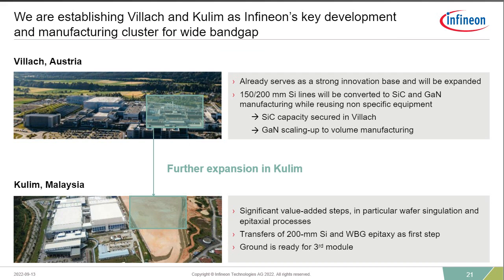And just highlighting the facilities here. We'll have a dedicated 150 and 200 millimeter production line for silicon carbide in Austria, and then the new facility coming online in 2025 in Malaysia, and sharing manufacturing. So this site in Malaysia alone, if it's just based on 150 millimeter, can generate about $2 billion worth of silicon carbide revenue. And if you increase that to 200 millimeters, which is the plan from the very beginning, you're looking at in excess of $2 billion.